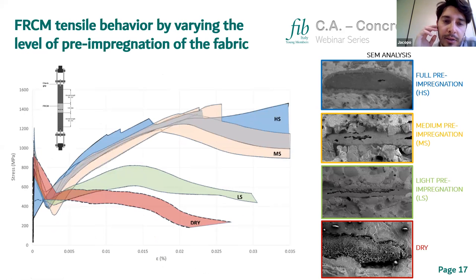These are other results on tensile tests that we performed on the same fabric, so on dry carbon fabrics. And then we also used a light pre-impregnation up to a full pre-impregnation with epoxy. Here you can see the stress strain curves of the FRCM when subjected to tensile stresses. In the case of dry fabrics, we have a softening behavior after the first crack, while by increasing the level of pre-impregnation, we have the shift to a strain hardening behavior for medium and for fully impregnated yarn.